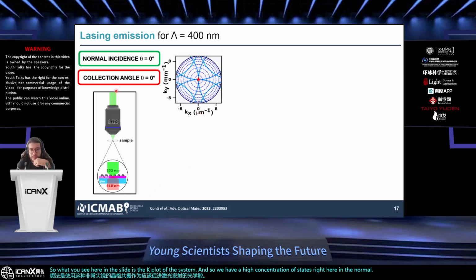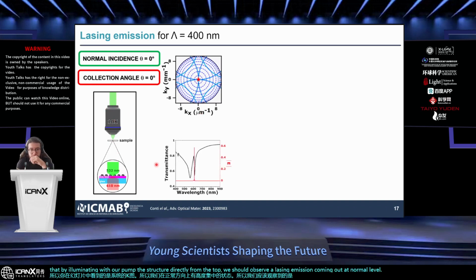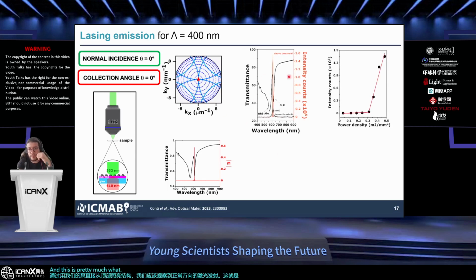So what we should observe is that by illuminating the structure with our pump directly from the top, we should observe a lasing emission coming out in the normal direction. And this is what the theory predicts. And this is pretty much what we observe. We have a very, very good overlap between the theory and the experimental data. And so what you see here in gray is the emission of the rhodamine B below threshold, so on top of our particles but below threshold. And here in red, you see how the